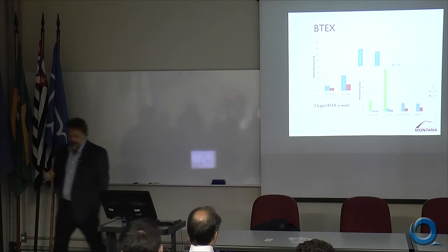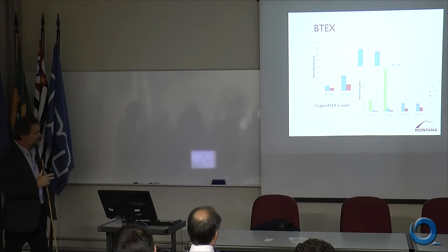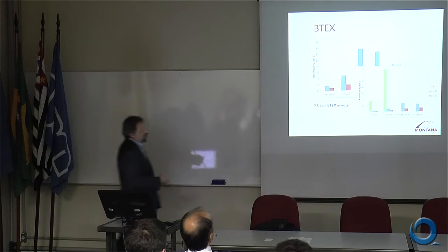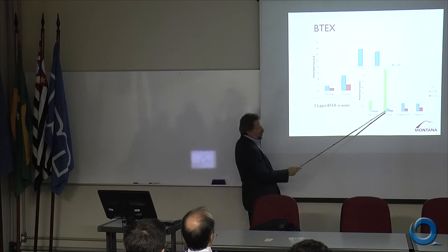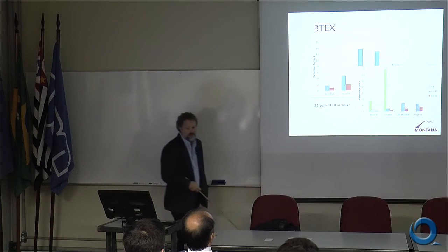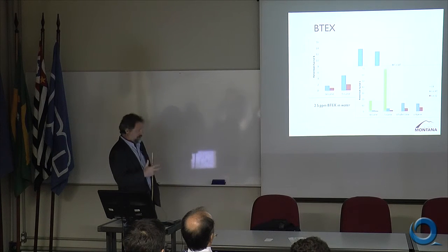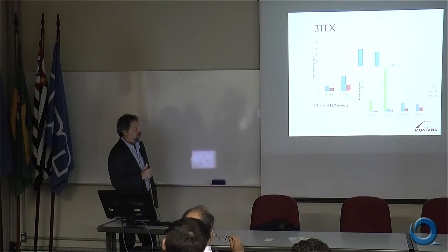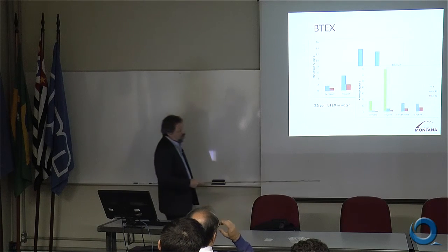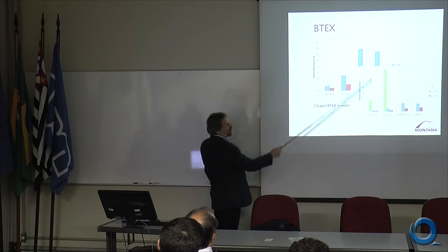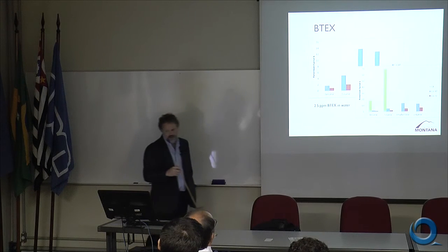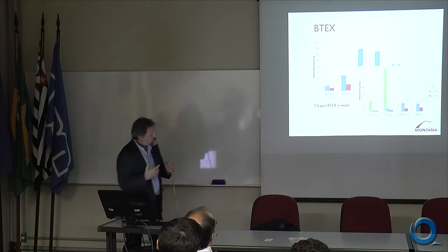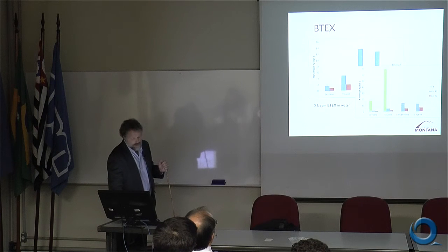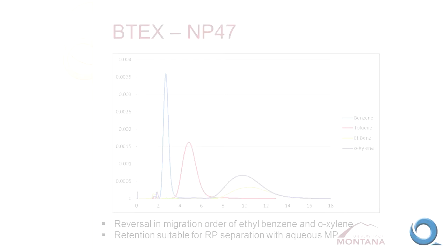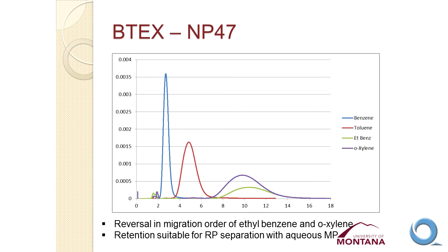So we do see extraction of these types of compounds. We could use these nanoparticle-coated surfaces to extract benzene or BTEX from water, but in fact, the performance of the nanoparticle surfaces is much less than that of conventional commercially available C8 or C18 materials. We tried to do this experiment with C18, and even benzene exceeds our ability to measure the retention factors. So we do see interactions, but much weaker than with octadecyl or octyl modified silicas.